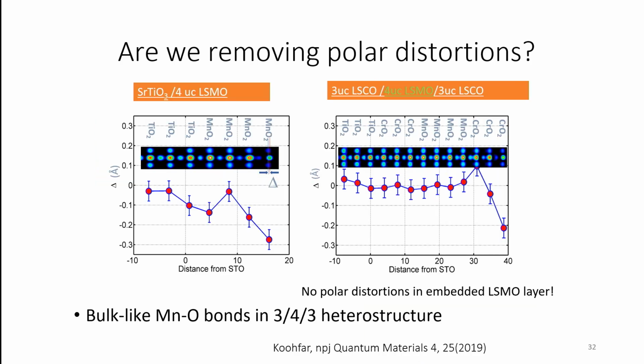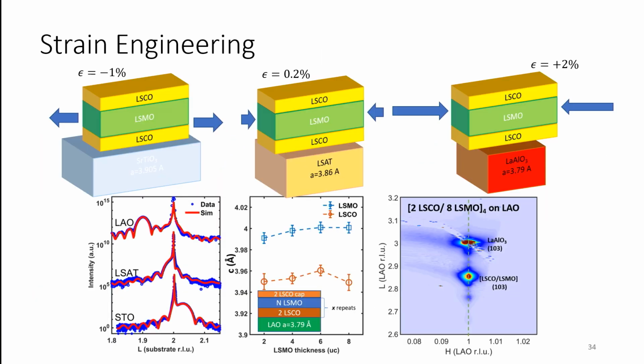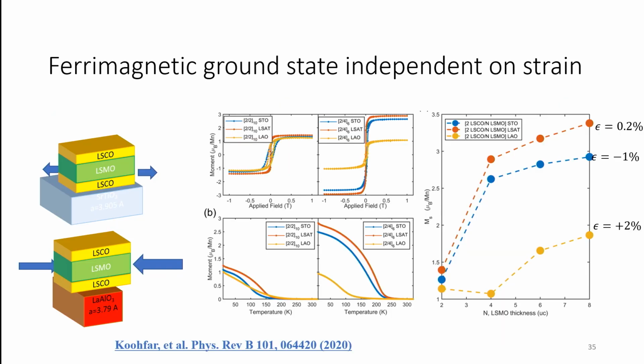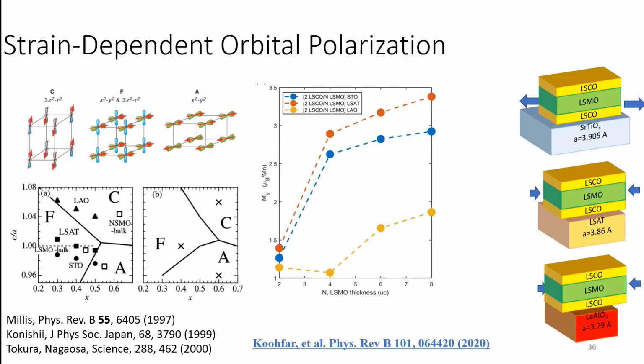All right, so we've confirmed using X-ray diffraction that if you have this sandwich structure, the distortions now go into the chromium oxide layers, and the manganese layers now have a bulk-like structure, they do not have these polar distortions. And that confirms, I think, our hypothesis that these polar distortions might be what is driving this thickness-dependent transition in the system. All right, so we have played around with strain, and we've looked at the effect of compressive and tensile strain by growing it on different substrates. We find out that for the very thin layers, if you have only 2-unit cells, there is no effect of strain, but as you increase the number of layers of the manganite in the superlattices we grow, we start to see effects that we can explain, which are related to the strain states of these systems.